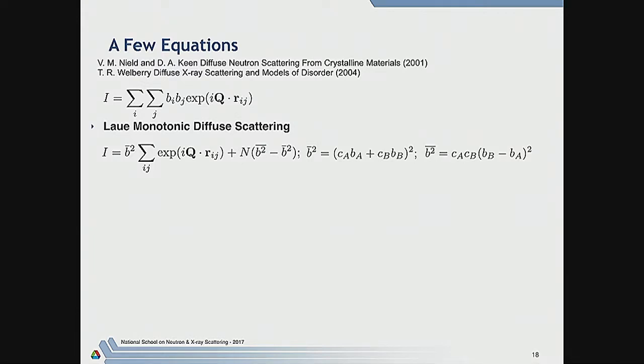If you have the completely random distribution, then the only diffuse scattering you have, this equation can be factored into two. You end up with the Bragg peaks. This is just the equation for all the Bragg peaks in here. But you also get a term which is exactly the same as you get for nuclear incoherent scattering.